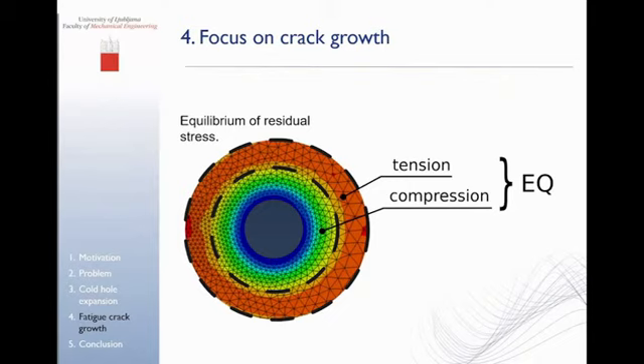So we have a ring around this compressive stress that is in tension. And tension again raises the fatigue load, so we believe that this is the cause that pulls the crack over the hole.